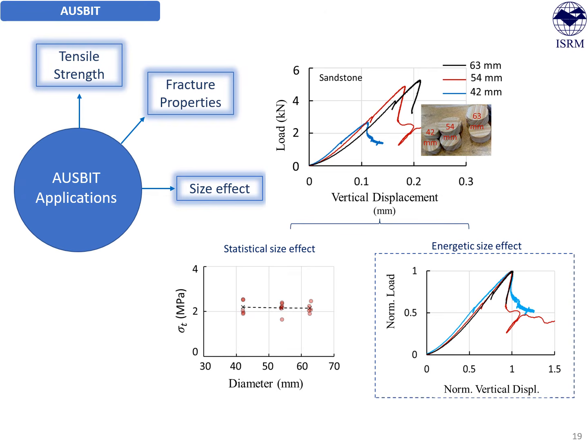Statistical size effect is that as we increase the size of the disk specimen, we end up getting lower tensile strength. This is because as we increase the specimen size, we can expect an increase in the inherent defects, and those inherent defects result in a relatively lower estimation of tensile strength. Now this statistical size effect can be evaluated from the conventional approach and from AUSBIT experimentation as well.